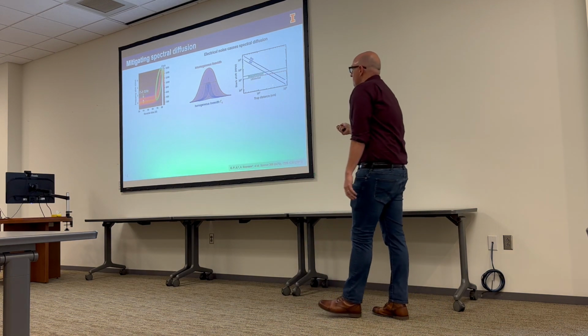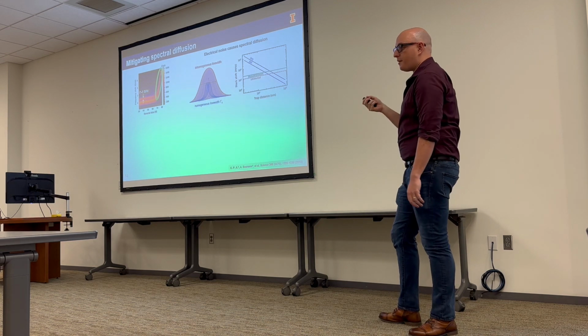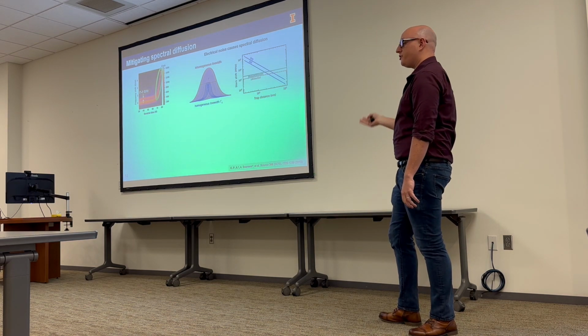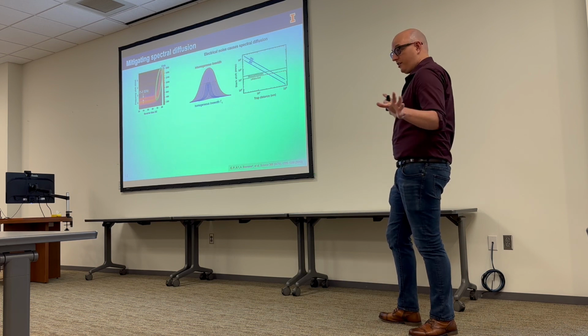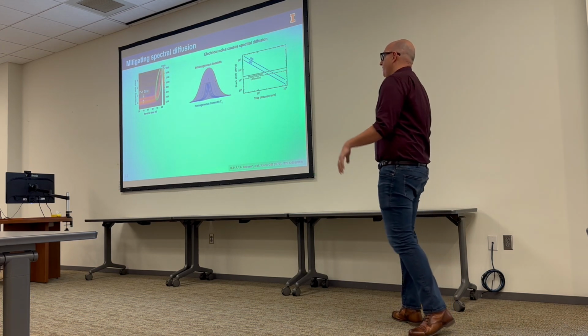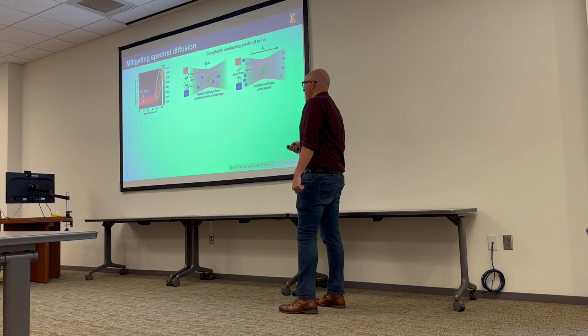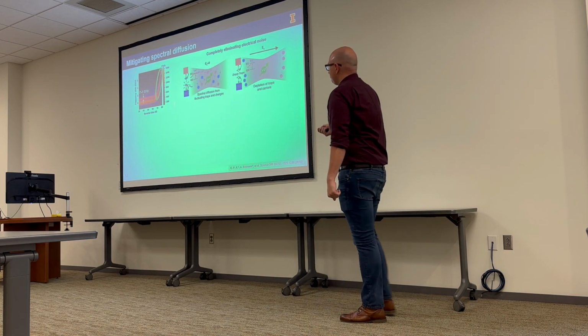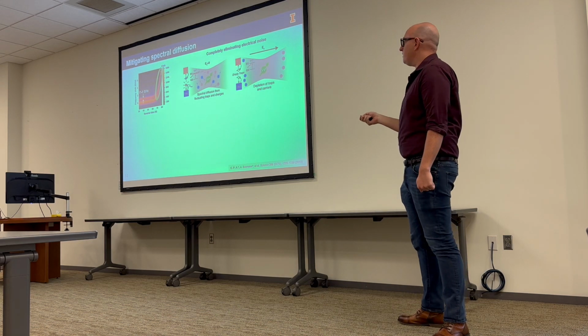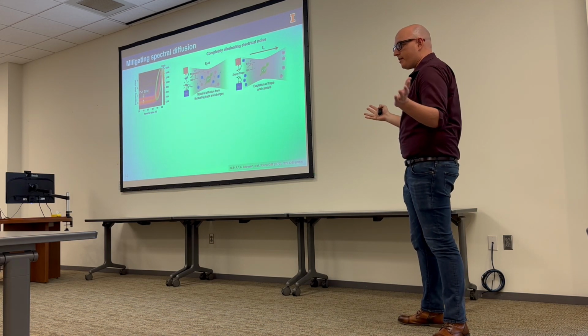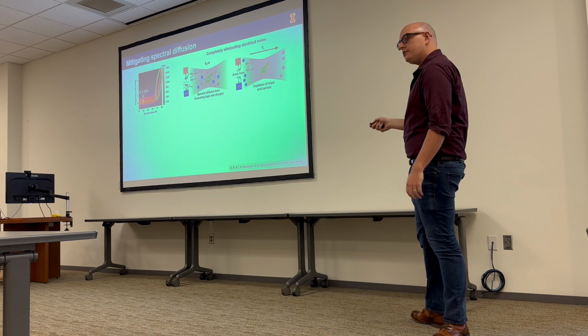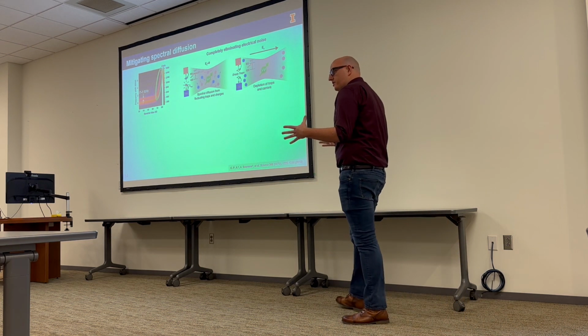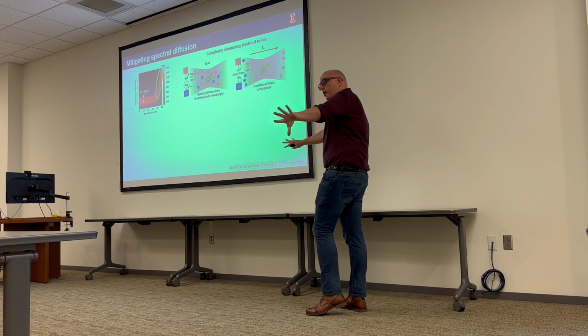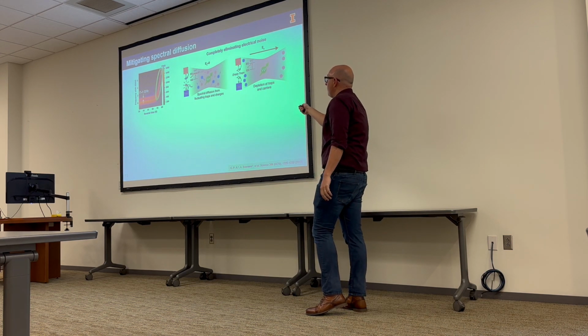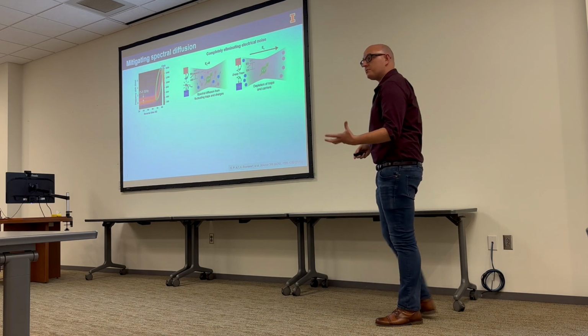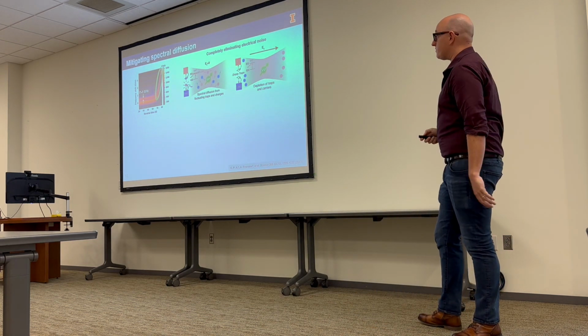It actually turns out that our system is so sensitive that we can sense the presence or the absence of a single electron, something like 200 nanometers away from our defect. So if there's any fluctuating carriers, you're screwed and your line gets broad. But that's why this narrowing is very exciting. Because this narrowing is basically telling you that under zero field, you have this fluctuating bath of crap, right? And if you start applying a field, you get this electric field in your crystal, you get this depletion physics. Those electrons and holes, they drift and diffuse away from your region of interest until you're left behind with a near perfect environment for your quantum system to live in that has no fluctuating carriers.